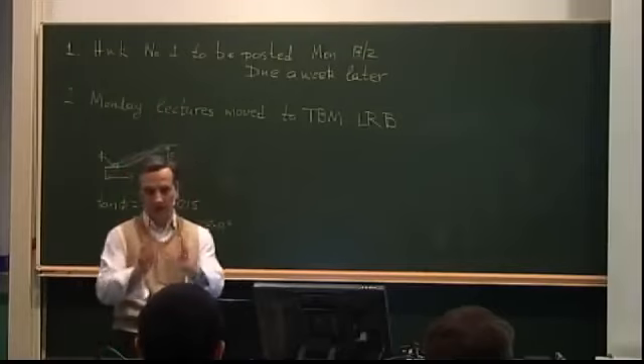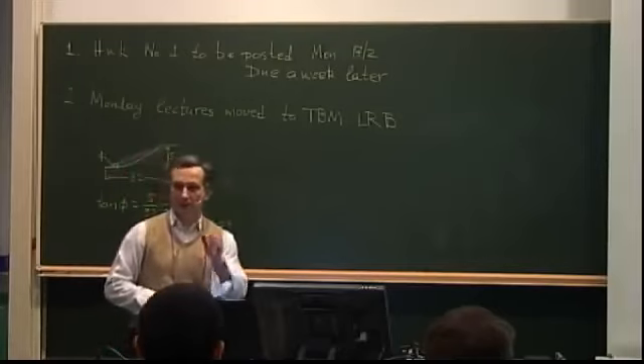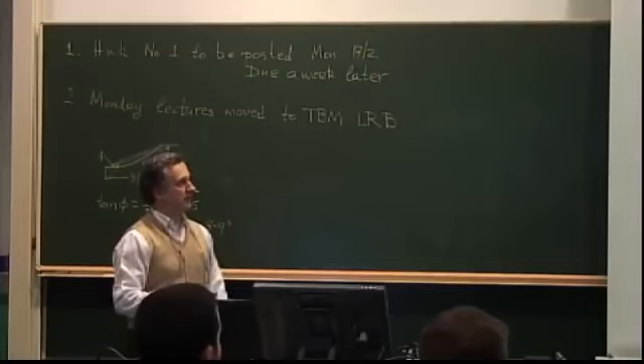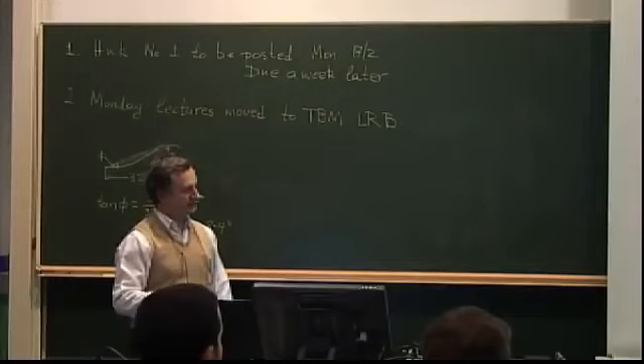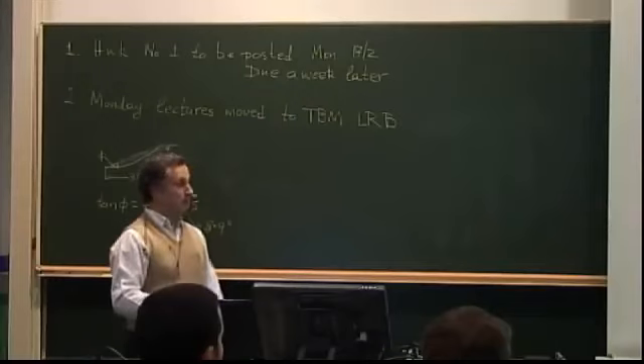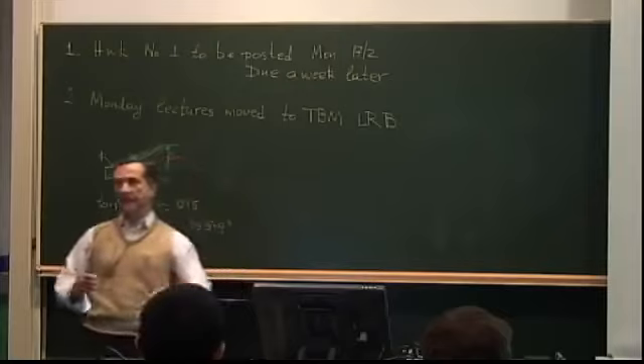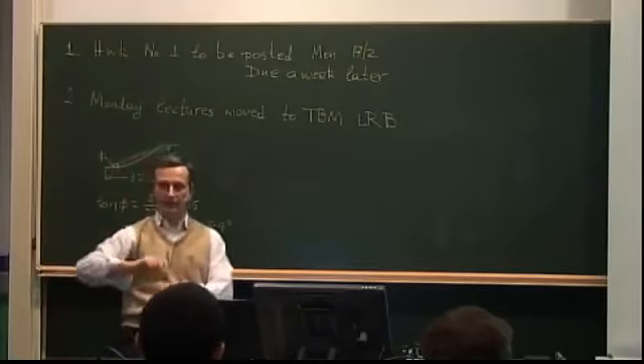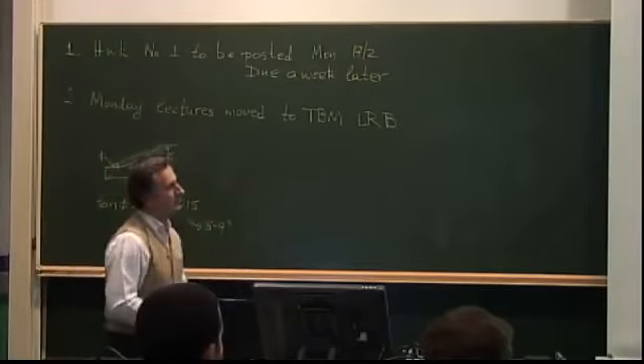If you look at a small enough piece of the composite or of the ply, you will see that they are wavy, and there are two theoretical possibilities: the in-phase case, where basically all the fibers are in phase, or the out-of-phase case, where they are 180 degrees out of phase, or of course the reality, which is a mix, and we don't do the reality because it's too difficult unless you do a Monte Carlo simulation.